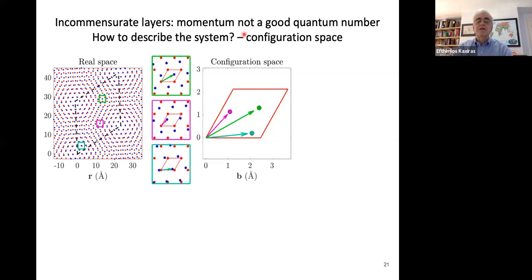Well, the answer to this very basic computational limitation came from a mathematical analysis, and it's referred to as working in configuration space. So the basic idea is that you have this kind of Moiré pattern again, with an overall apparent periodic cell, and you can focus on different regions and look at the local environment of the atom in one layer, depending on where the atoms in the other layer are. So the two layers here are colored red and blue. And you find lots of different local environments depending on where you are. And you can describe those in configuration space.